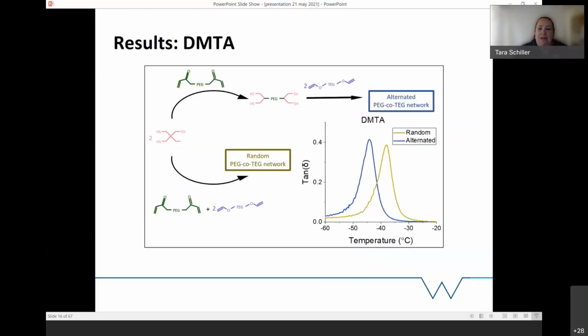I have no idea. So when we look at the network change here, we add the more random network here compared to the system we've made, and we get quite a bit of a change in the performance of the material. This isn't unexpected because we've now started to control the system a bit better. So what's cool about this is then we can start to tailor the actual properties of the system.